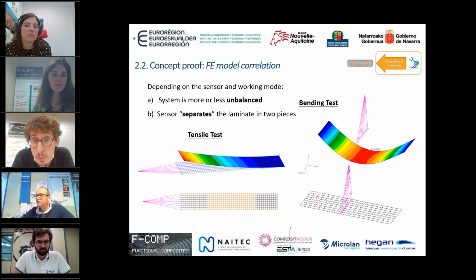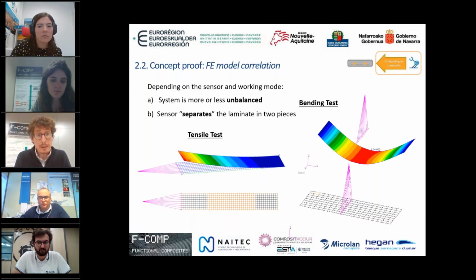And related with the explanation that I gave about the shear transfer, in the bending test, this is clearly how, depending on the substrate, if we don't have a very good shear transfer, the bending test fails quicker. This is because the two materials separate, the sensor separates, and then it breaks the part that is thinner, and then it breaks the other part. So this is the failure mode in the bending test.